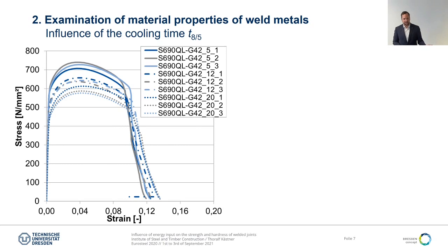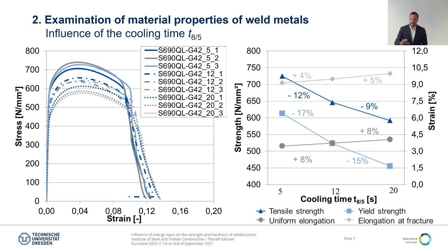Again, on the left side we have stress-strain curves for 3 different cooling times of the material combination S690QL in combination with a G42, for the cooling times of 5 seconds, 12 seconds and 20 seconds. And having again a look at the mechanical properties, we can see that we have a large reduction in the strength and an increase in the ductility of the welds.